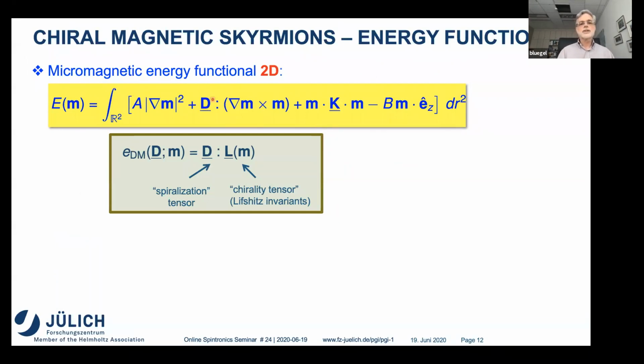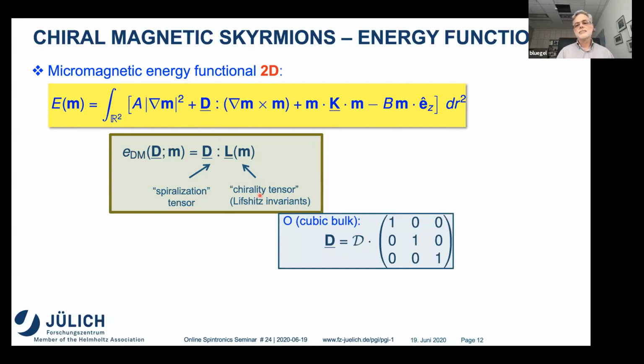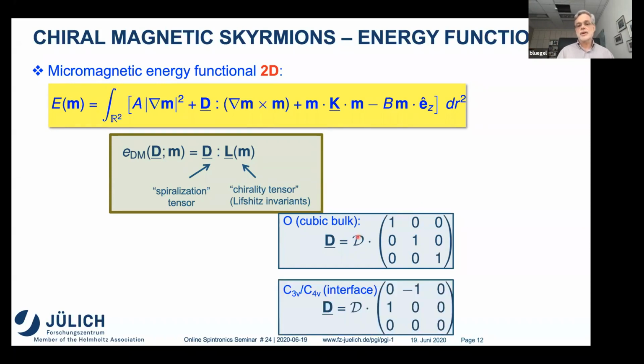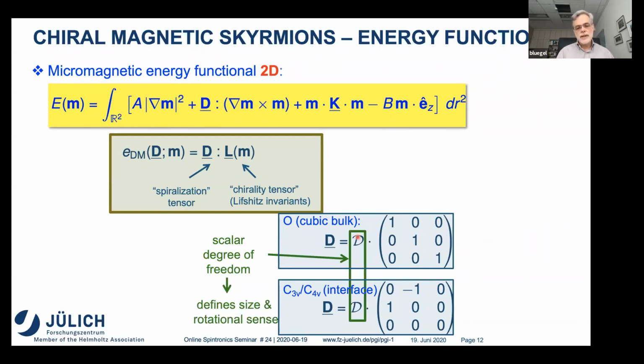Let's have a closer look at this Dzyaloshinskii-Moriya interaction again, which we can describe by a Dzyaloshinskii-Moriya spiralization tensor and by a chirality tensor. You can write it down, and basically the crystal structure determines the structure of this chirality tensor. So your Dzyaloshinskii-Moriya interaction is given by a tensor quantity and a scalar quantity. Different geometries lead to different tensors. So you have one scalar degree of freedom, which defines the size, and the sign defines the rotational sense.